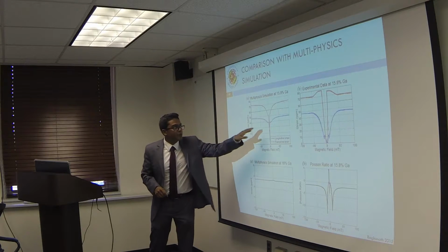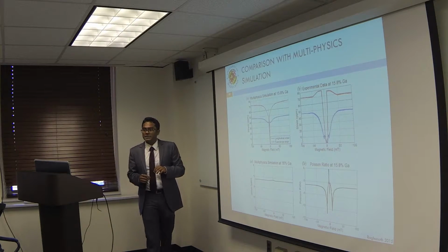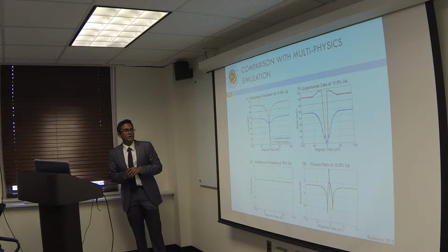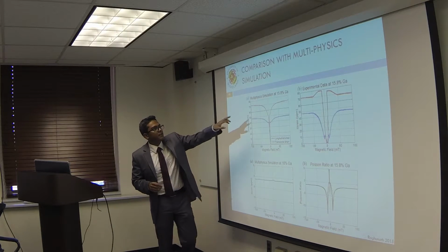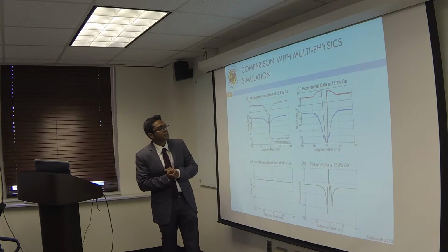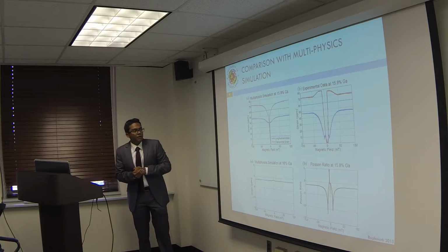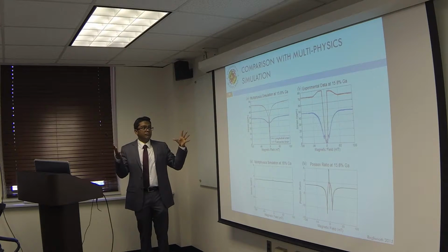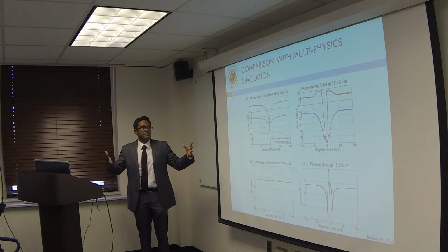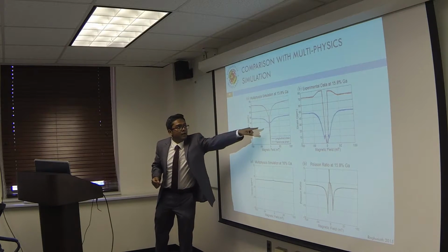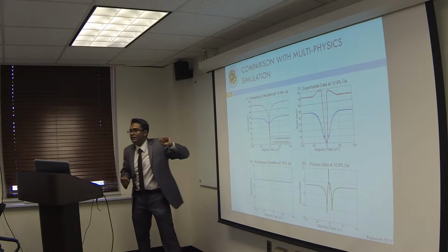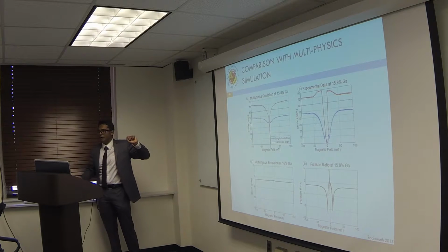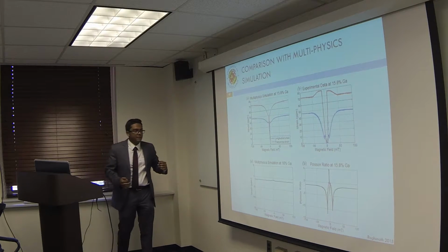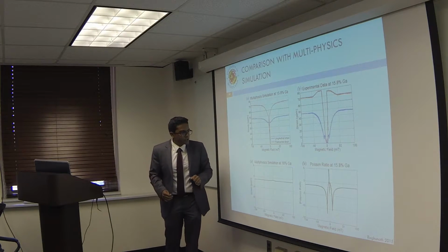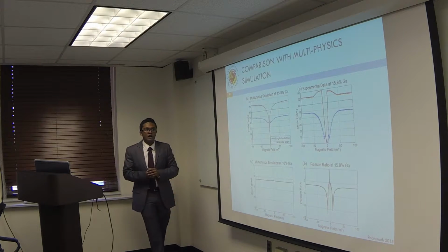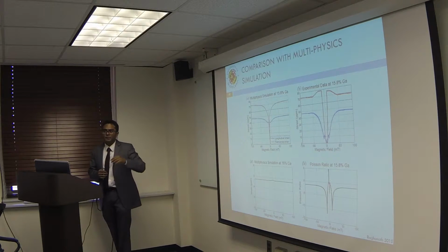It was also able to predict the non-monotonic increase that you see in the strains along the longitudinal direction, but it didn't predict the decrease that we observed along the transverse direction. But this was very exciting because this could actually predict the trends in the strains, and we did not see this small weird bump in the longitudinal direction where we did the simulations at greater than 20%. And the error in the value of Poisson's ratio at magnetic saturation was also less than 10% when compared to the experimental data.